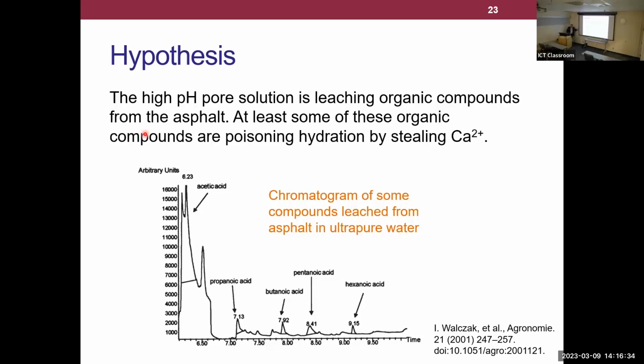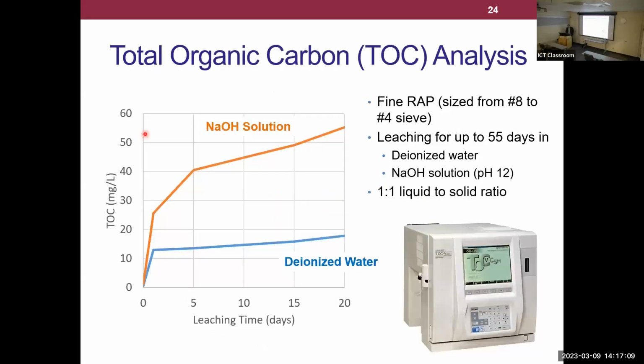So our hypothesis was, when cement hydrates, it produces a very high pH pore solution. In a saturated concrete, those pores are not filled with air, they're filled with pore solution, a high pH pore solution. So our hypothesis was that this high pH pore solution is leaching compounds from the asphalt on the RAP, and that is somehow poisoning hydration, somehow preventing hydration from happening. That was our idea of what's going on here. So then we set off to see if that hypothesis made sense.